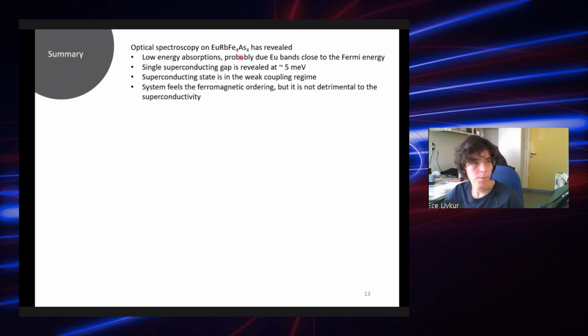So with that, let me summarize the optical spectroscopy on the europium 1144 system. We managed to observe the superconductivity on that system, and the optical spectra sees only one superconducting gap at 5 millielectronvolt, and we suspect that the second gap is in the clean limit. I think this is also one point that still looks for some confirmation. And then the system really feels the ferromagnetic ordering, but it's not very detrimental to the superconductivity. And there are some low-lying absorptions, probably due to the europium bands close to the Fermi energy. That would also be nice to confirm at some point.